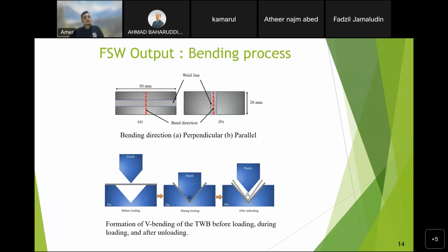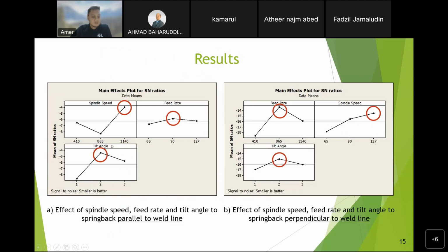So this is the friction stir welding output, which is the bending process. Two springback values were measured for different welding directions, which are perpendicular and parallel. The springback value is calculated by subtracting the loading angle theta 1 and unloading angle theta 2 as shown in the figure. So these are the results from the experiment designed by the Taguchi method. This is the main effect plot for the SN ratio.